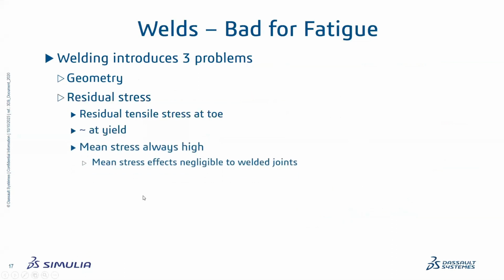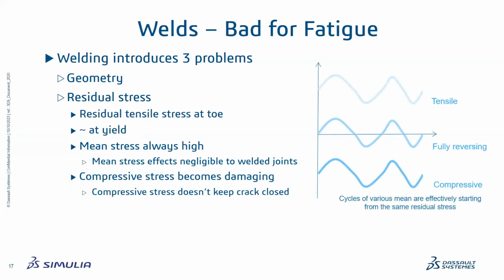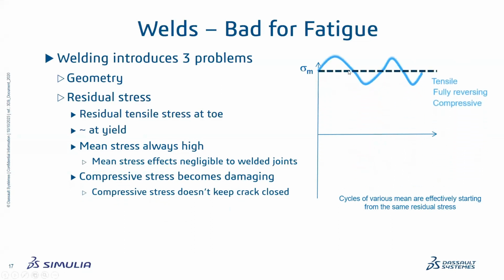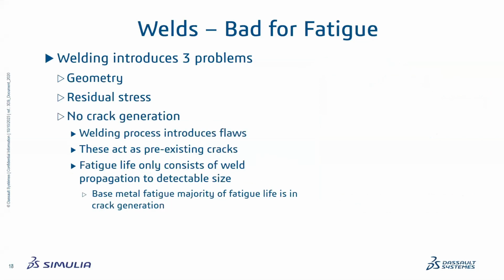There's then also a residual stress effect, which means that when you weld it up, you're melting the material and then it cools down. And so there's a residual tensile stress there, pulling, particularly at the weld toe. What that means is that in base metal fatigue, if you've got reversing cycles like compression in your load history, that typically is not considered damaging. But when you superimpose that on a residual yield-level tensile stress, even the compressive cycles become damaging because you're cycling a fully tensile state. So that's again another reason why welds are bad.